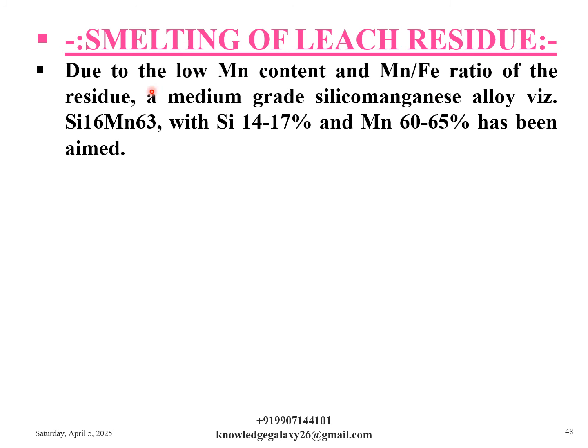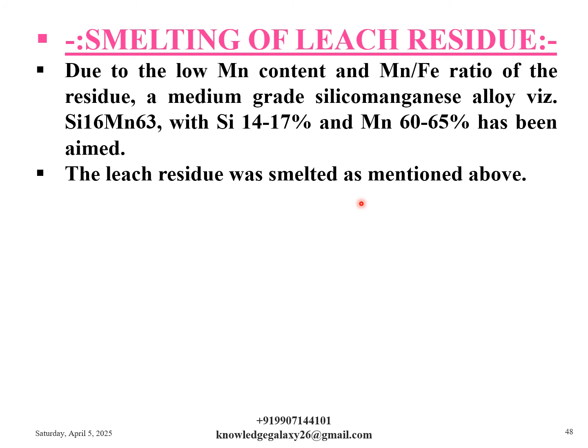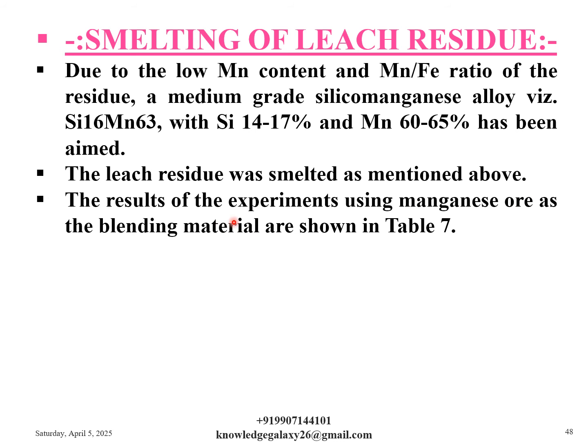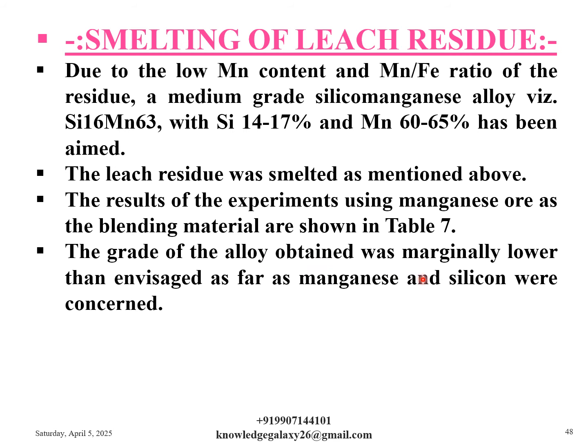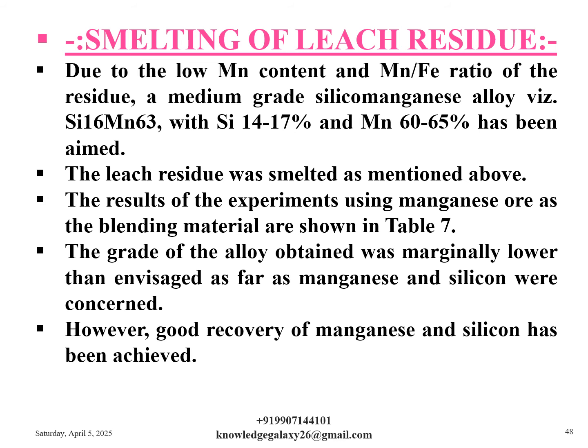Now let us move on and discuss the smelting of leach residue. Due to the low manganese content and Mn by Fe ratio of the residue, a medium grade silicomanganese alloy, with silicon 14 to 17% and manganese 60 to 65% range, has been aimed. The leach residue was smelted as mentioned above. The results of the experiments using manganese ore as the blending material are shown in table 7, which is given in the next slide. The grade of the alloy obtained was marginally lower than envisaged as far as manganese and silicon were concerned. However, good recovery of manganese and silicon has been achieved.